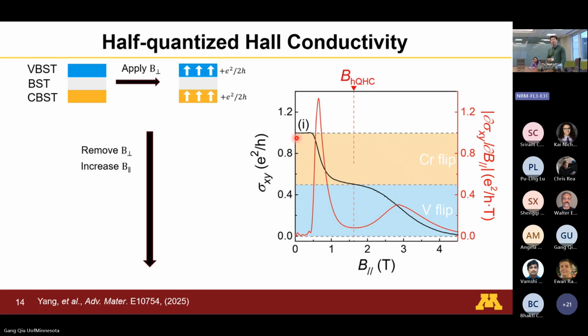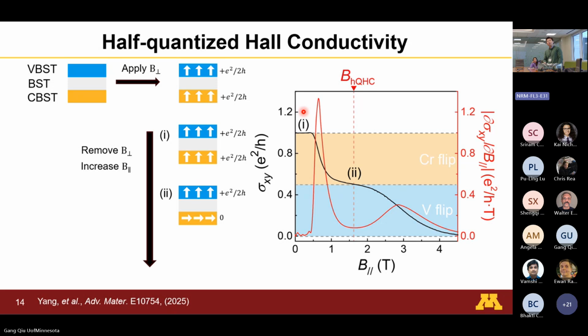Okay, so we start from here. If you look at the Rxy or sigma xy, it starts from 1. That's your quantum anomalous state because it has a PMA. It takes a little bit of in-plane field to rotate it into the in-plane direction. Okay, now move on to this intermediate state. Now, the softer chromium layer will be pulled into in-plane configurations.